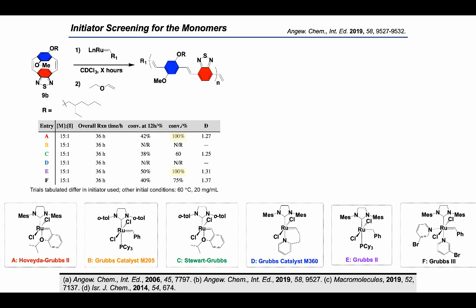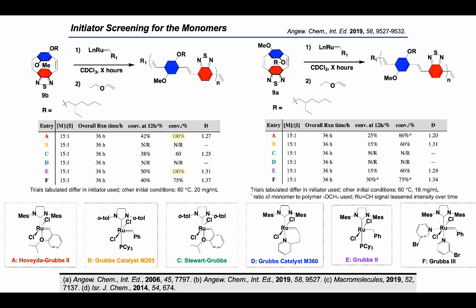While not all initiators reached complete conversion, all of them did exhibit low molecular weight distributions. We performed similar screening for the other isomers shown on the right. In this case, none of the initiators reached sufficient conversion, but again, all achieved low molecular weight distributions. Considering the lesser conversion, future polymerizations focused on the monomer on the left. That said, the difference in reactivity by varying the position of the larger alkyl chains is of considerable interest to